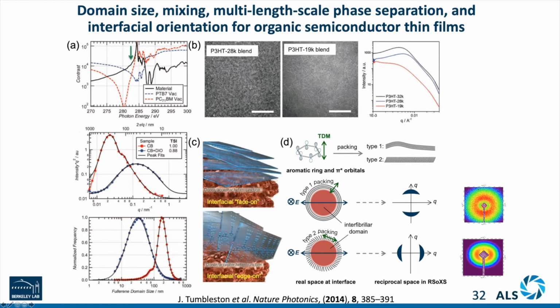actually give us a unique perspective looking at the interface between the amorphous region and semi-crystalline region, because that will give us an overall different form factor. The effective form factor will be related to the incident X-ray beam polarization at resonance. At non-resonant condition, that's not visible, but at the resonant condition, if you come in vertical polarization, you can see the form factor become like a rod vertically. If you come in horizontally, the form factor become a rod laying horizontally. So that is reflected in the anisotropy scattering,